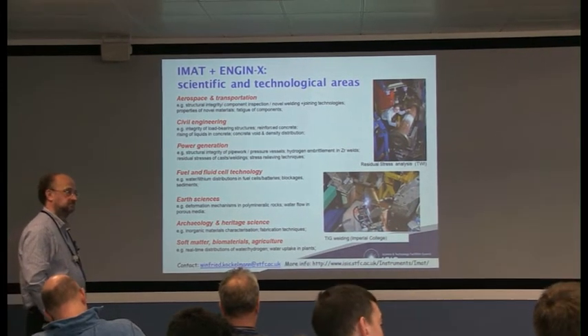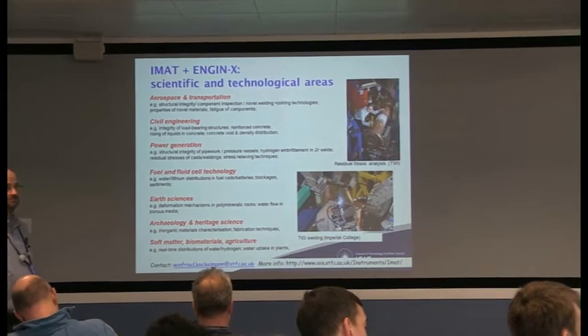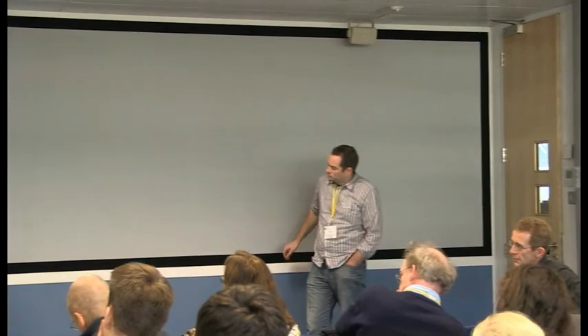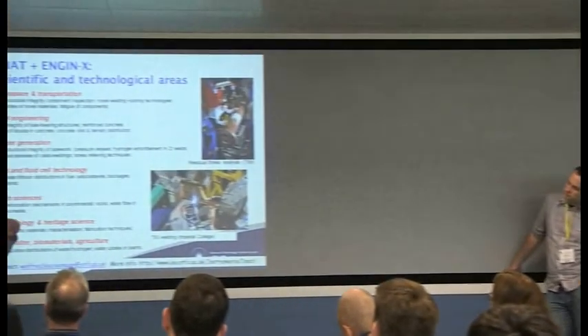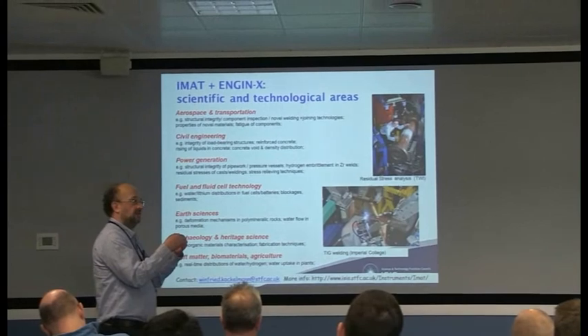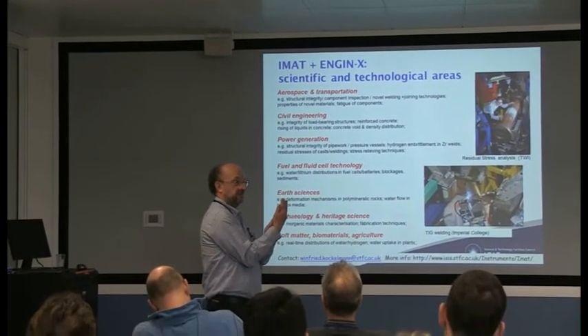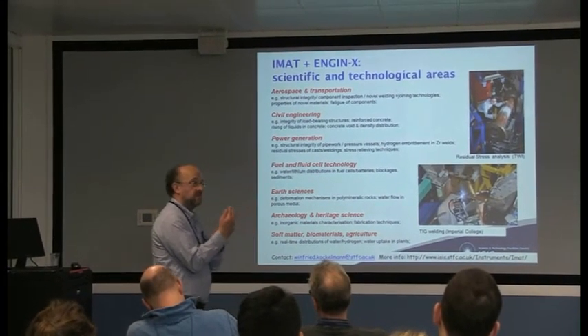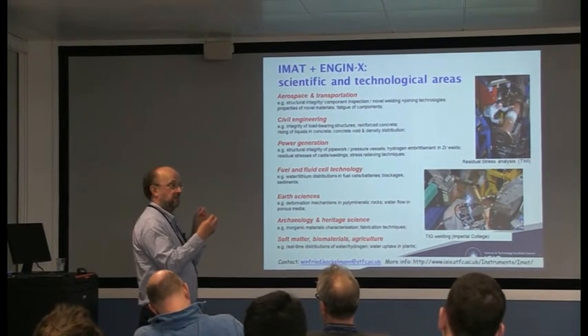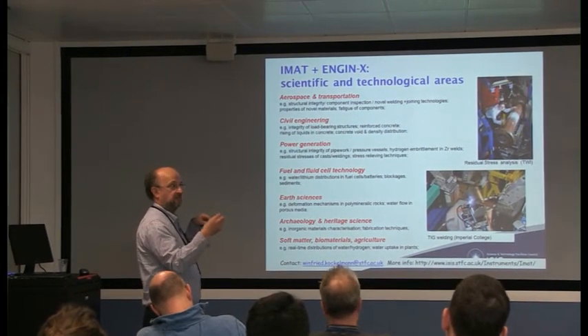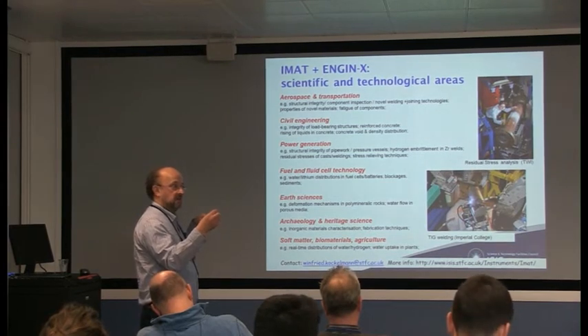The other thing was that the time-of-flight method is so much slower than X-rays. What specifically does the ability to do time-of-flight measurements give you with different imaging? What we actually do is we measure the energies of the neutrons via a flight time measurement. So that's actually what our detectors do. The measured variable is the time, from the generation in the source up to the detection in the detector.